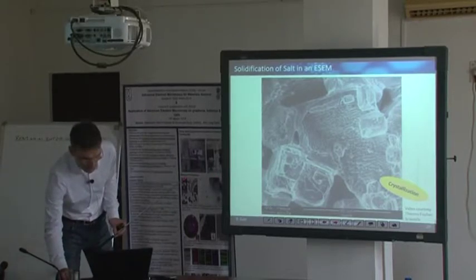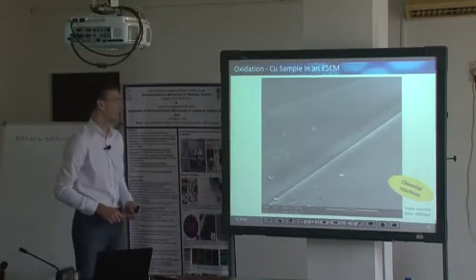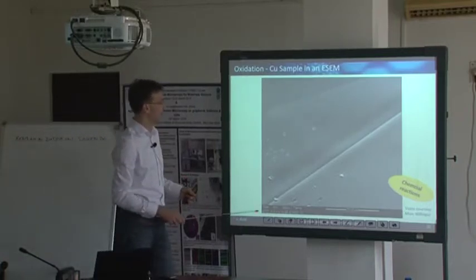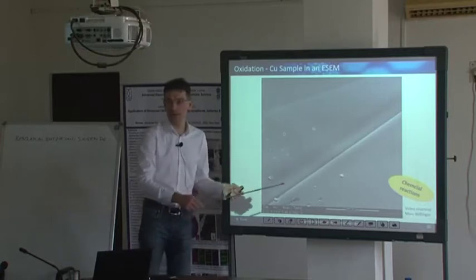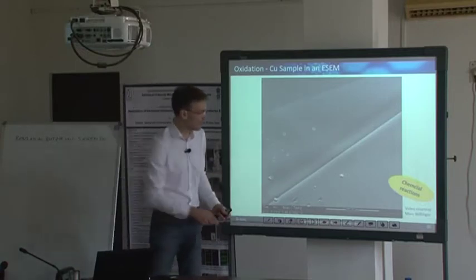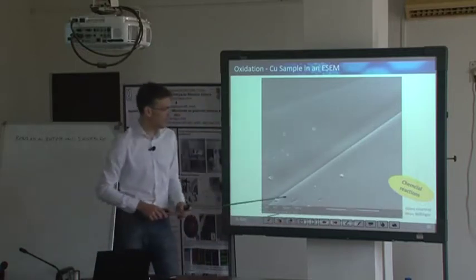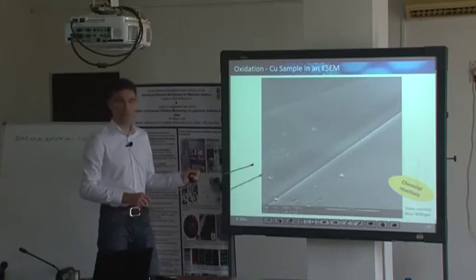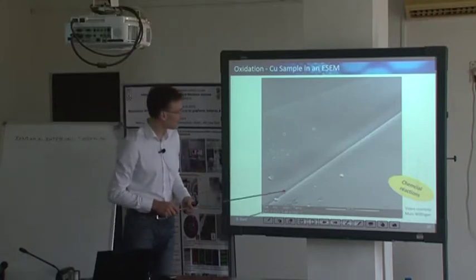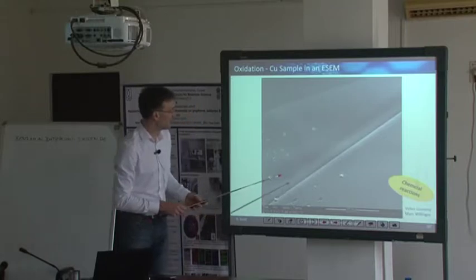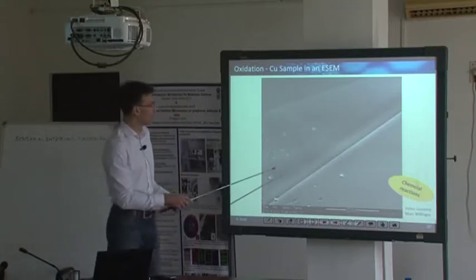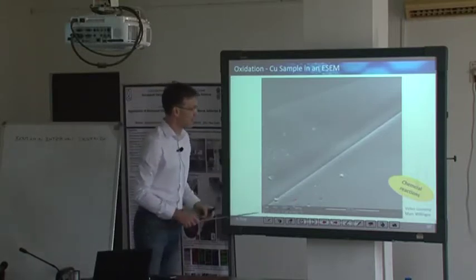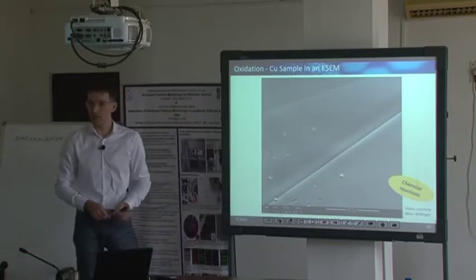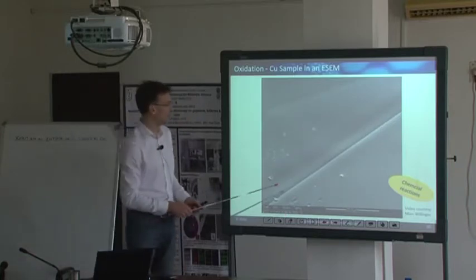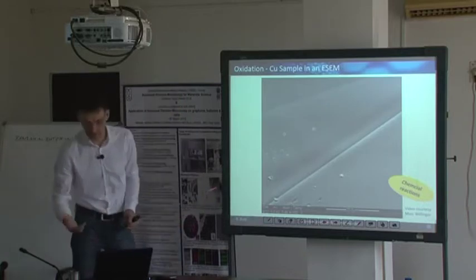There are two more examples which are more relevant to applications. This is a copper surface, a very nice and clean sample. I got these from a colleague from Berlin, Marc Willinger. These are not published, but nonetheless I would like to share them here. So this is a copper surface in an oxygen environment at slightly higher temperature, and this is about the oxidation of a metal.